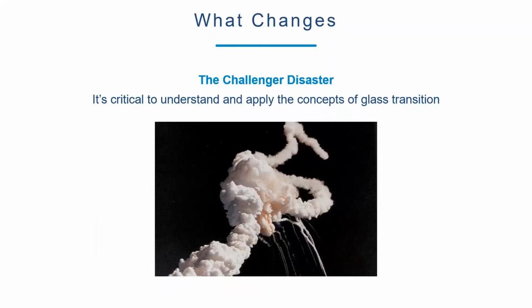The Challenger disaster is one of the most famous examples of materials used outside the appropriate temperature range. Segments of the solid rocket motors were stacked together, and the joints to join those segments were sealed with a rubber seal. When launched on a cold morning, the seal failed. It was later determined that the material was below its TG and the rubber seals had stiffened, contributing to the accident. So the joints were redesigned with a different seal configuration, in fact, multiple seals, and a different material was selected before launches continued.